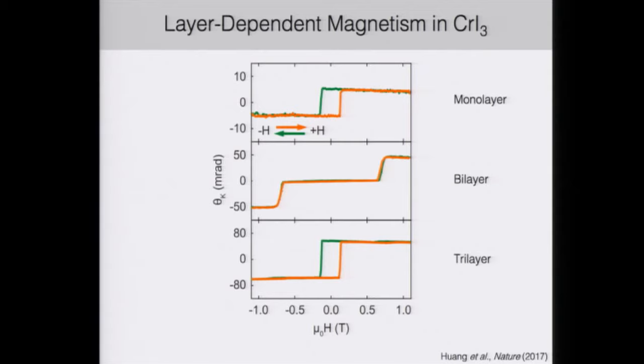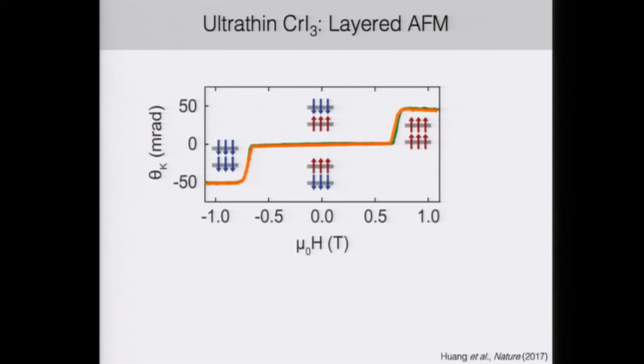Yeah, so these results really confused us at first because we expected to see a magnetic signal in the bilayer. And so what we ultimately came to understand is that ultrathin chromium iodide, unlike the bulk, is actually a layered antiferromagnet. So we can think of the ground state of the bilayer as having this layered antiferromagnetic up-down or down-up state.